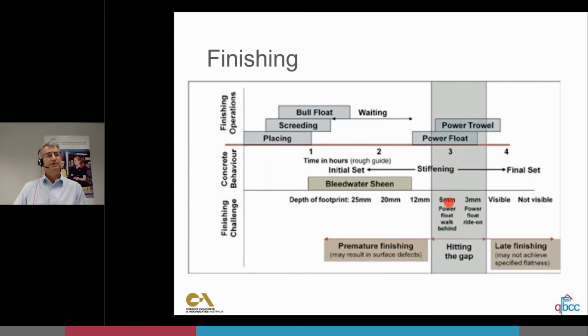And when a boot print is no more than 6 millimeters, we can get on with a power float. And when it's no more than 3 millimeters, we can get on with a ride-on float. And that's hitting the gap. So we're getting on there while it's still soft enough to level, but after that bleed water has evaporated.